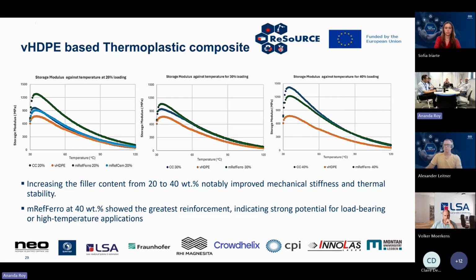Moving further, looking into the mechanical thermal analysis of this material within a different temperature sweep, especially the storage modulus across the different temperature regimes. One trend that we can observe is that with increasing temperature, the storage modulus decreases. This is very typical of thermoplastic behavior. With increasing temperature, you can see the softening and reduction in mechanical rigidity.